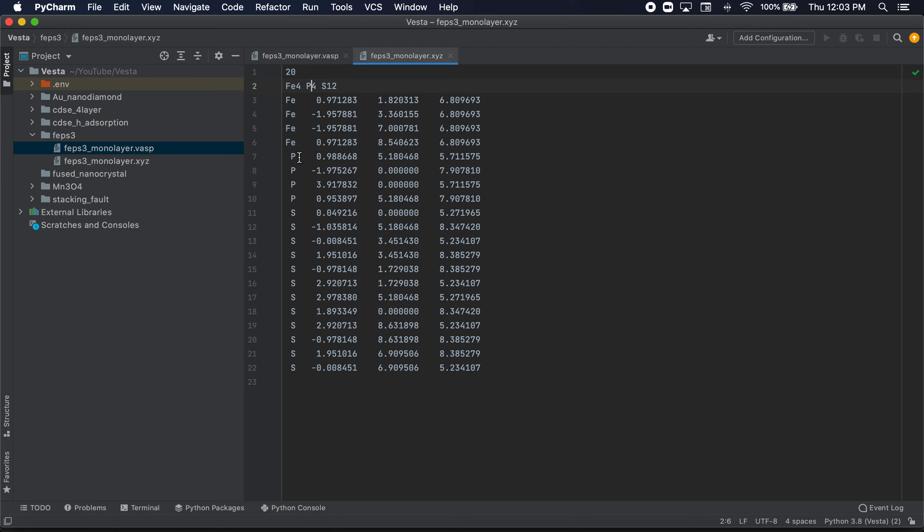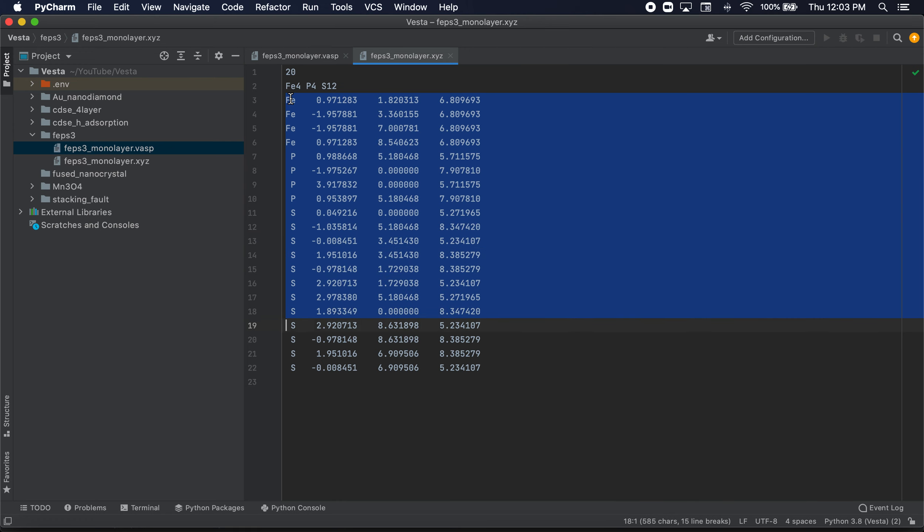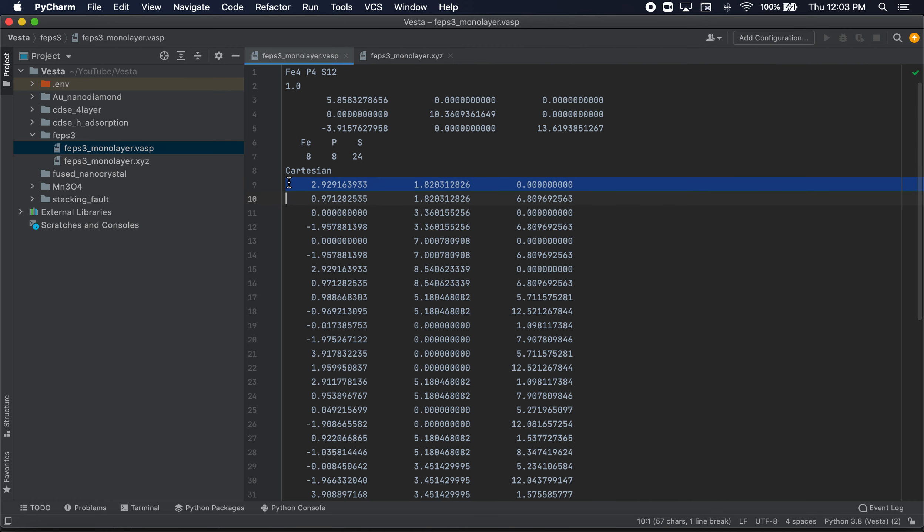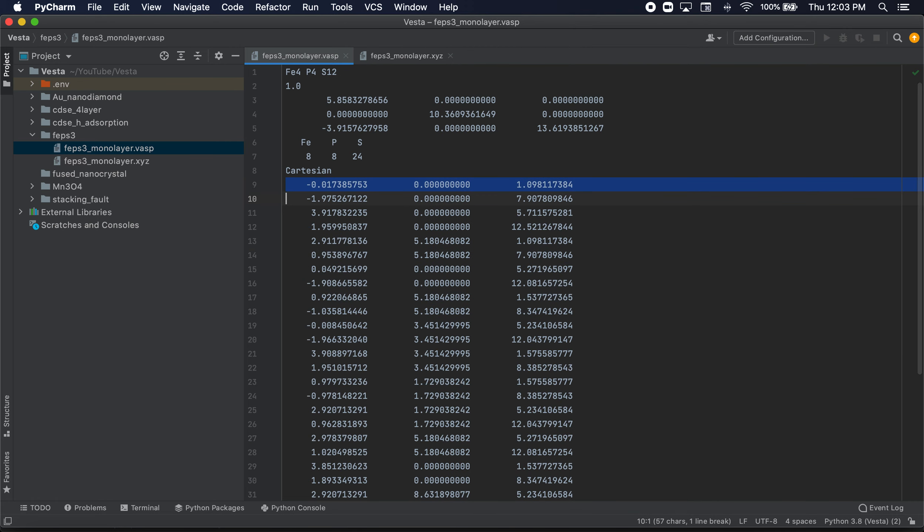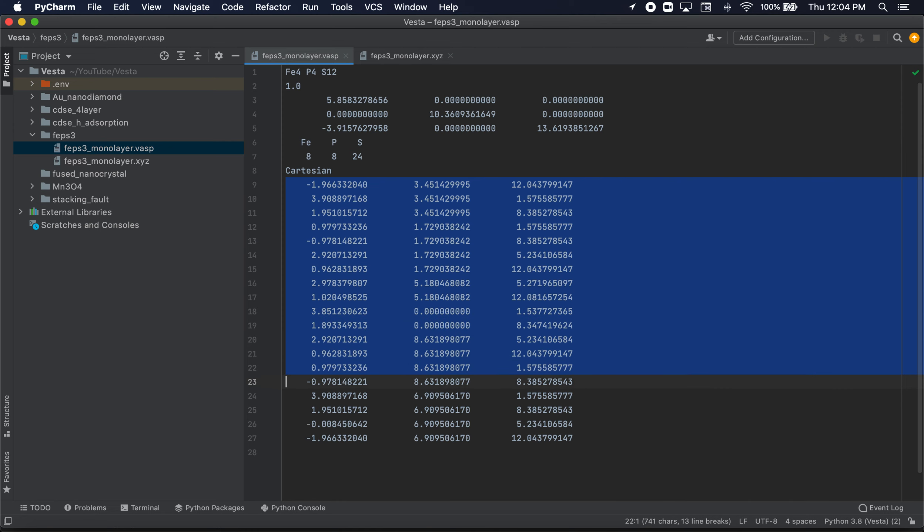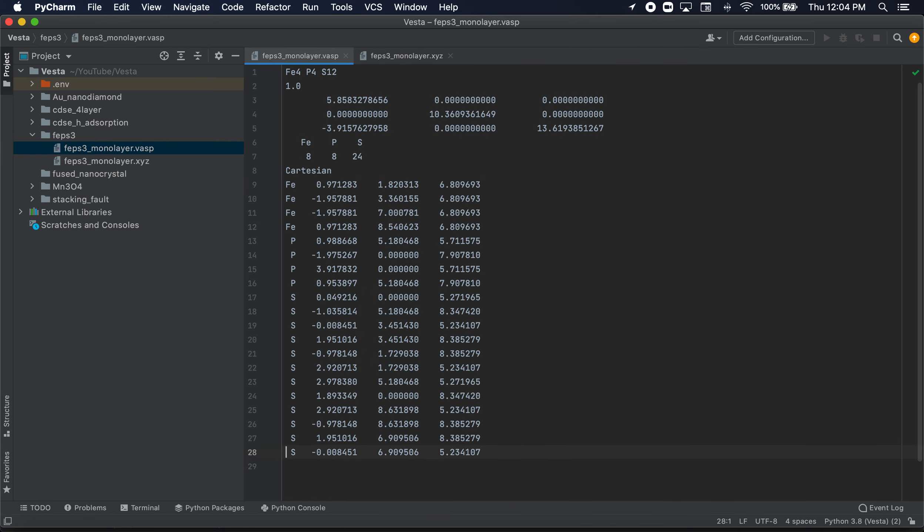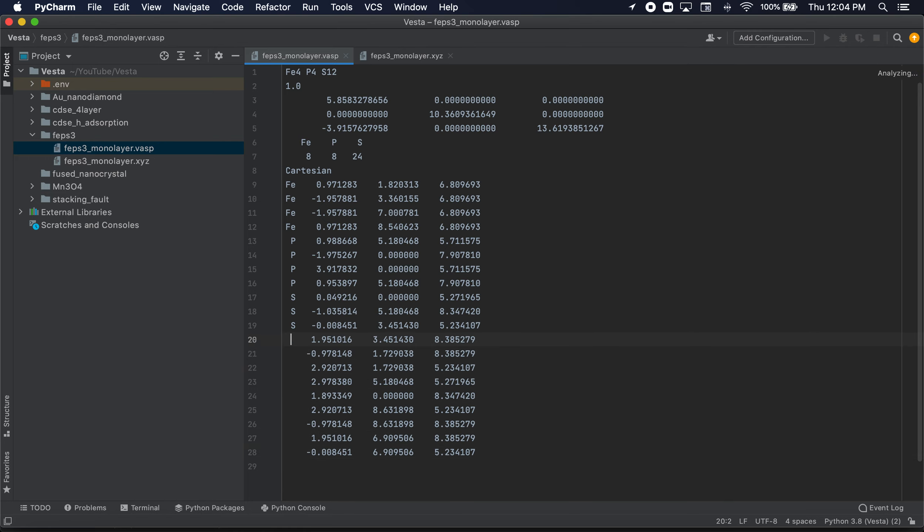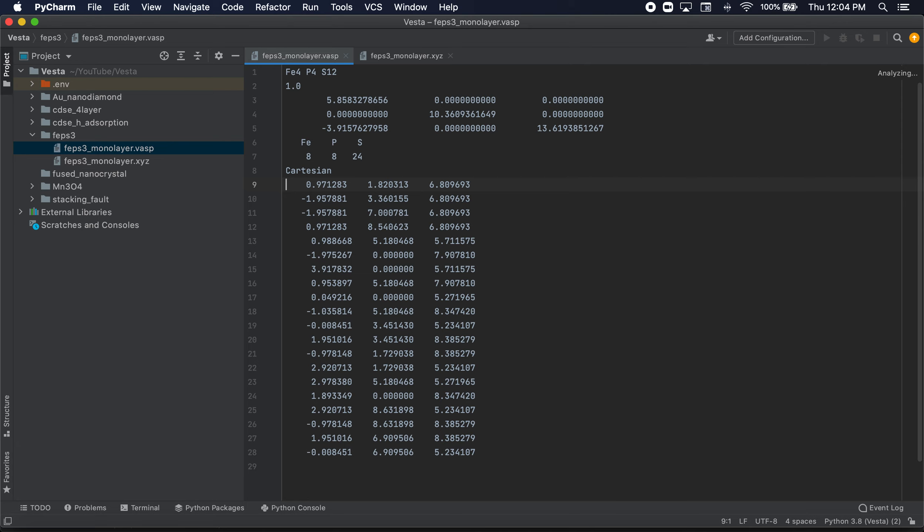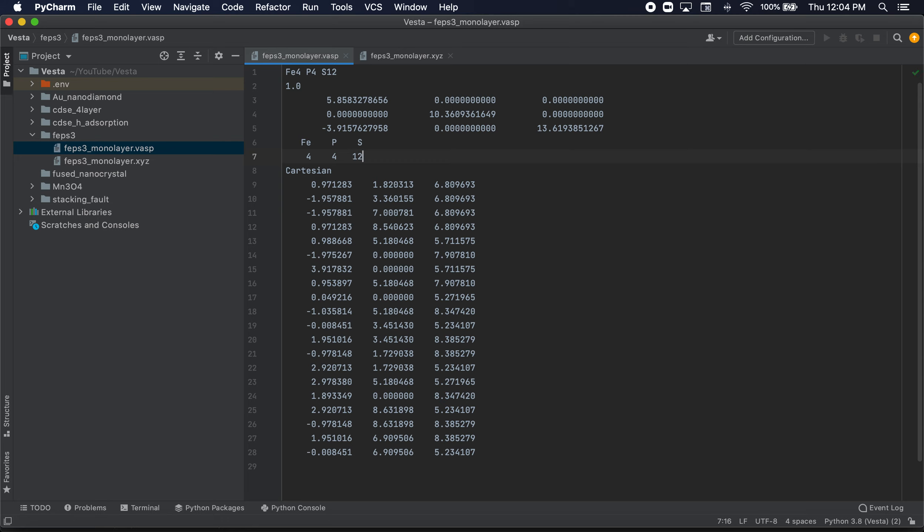So the XYZ will contain less because we had cut a lot of atoms out. One thing to notice though is that the stoichiometry is still correct. We have four irons, four phosphorus, and 12 sulfur. So what we do now is we go ahead and copy these coordinates. 4, 4, 12, remember that. And we paste them into here. I'm just shift drag deleting these. OK, so let's go ahead and delete these now. So we delete the title here, the atom symbol. Because it's read from these two lines here, so the first four will be iron, the following four will be phosphorus, and the following 12 will be sulfur.